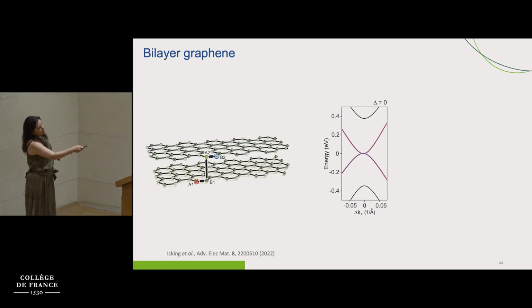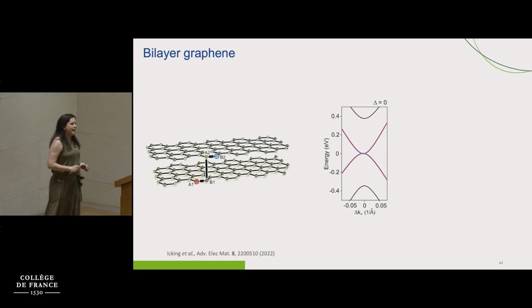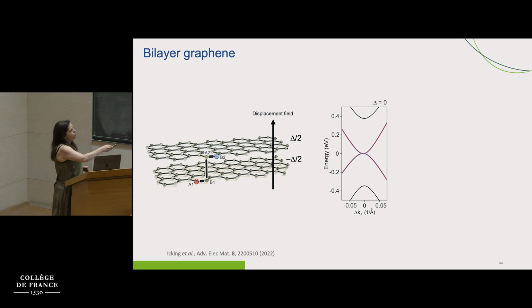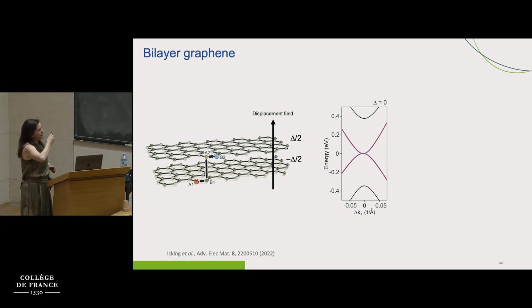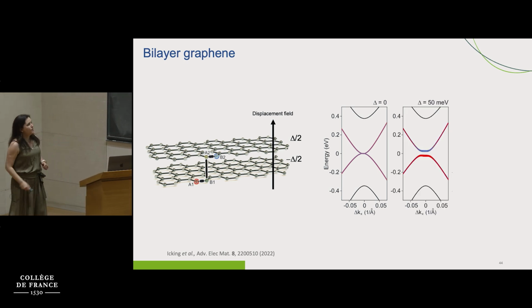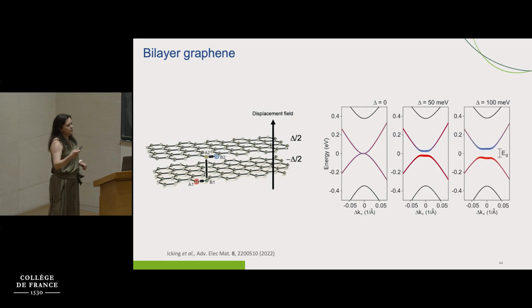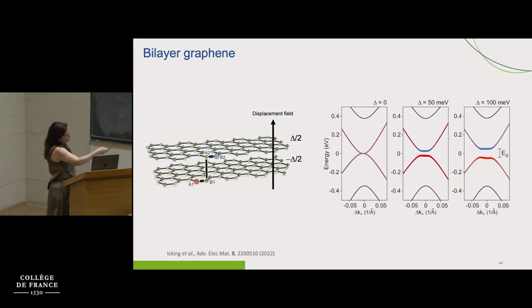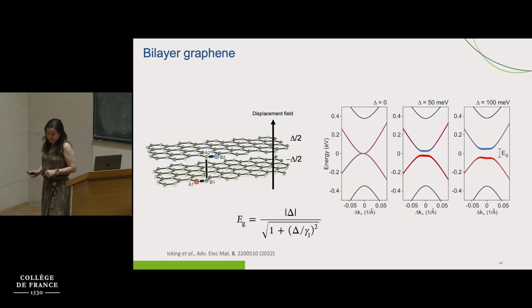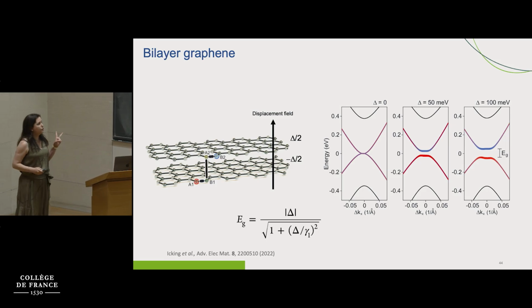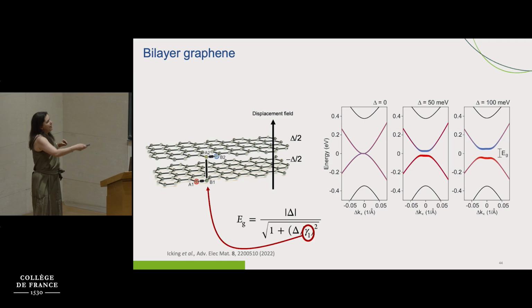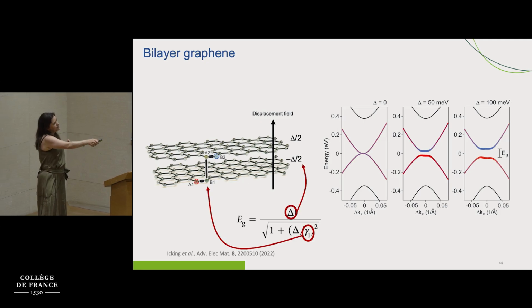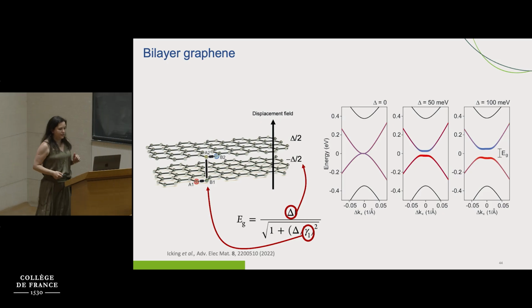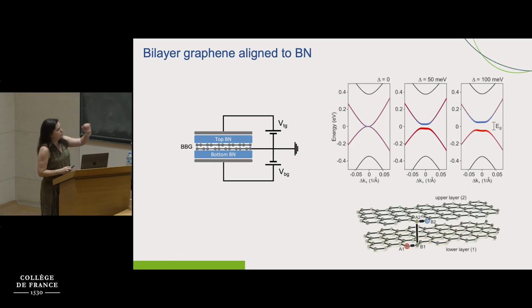Our band structure is now going to be parabolic. And more interesting, now we are able to apply a displacement field, so an electric field perpendicular to our sample. And with this, by changing its magnitude, we are able to tune a gap in this system. This gap is only going to depend on 2 things. The first one is the interlayer hopping, and the second one is the difference in potential between the 2 layers. So let's put this aside.